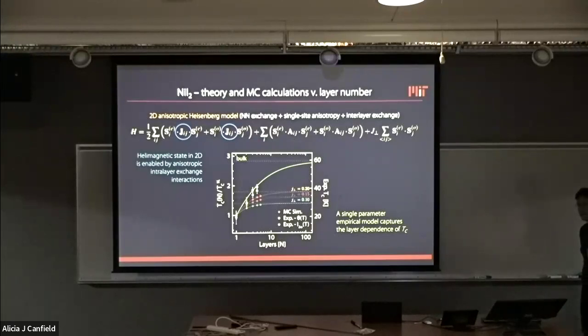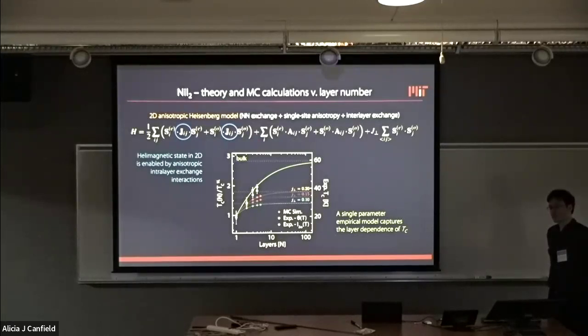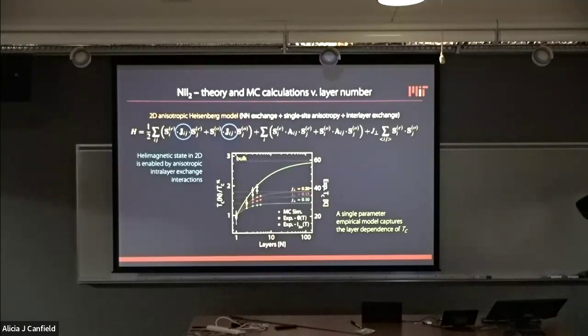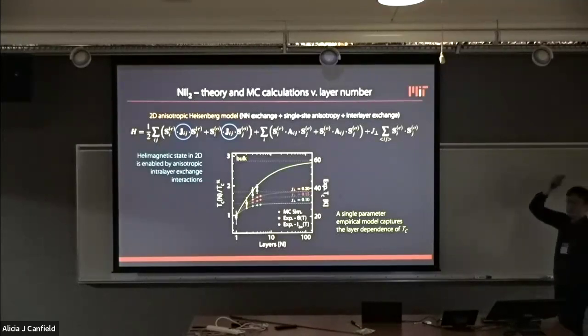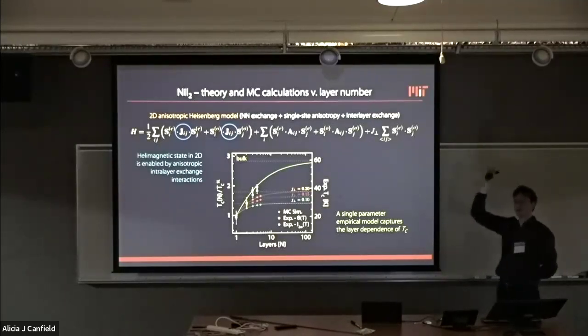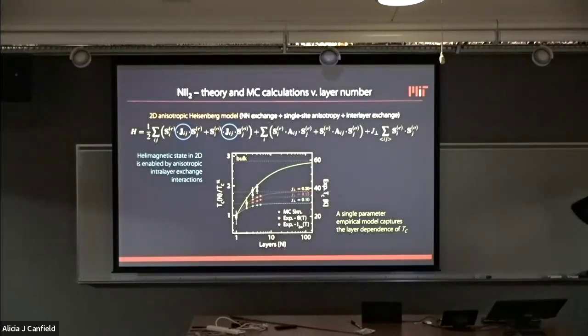So a question about this monolayer limit. If you apply a magnetic field, don't you expect a first order transition into a Skyrmion crystal? Yes, and this has been observed in several systems that start off with a 1Q state, and then you can stabilize a 3Q state. This particular material, nickel iodide, for reasons that I don't fully comprehend, but the theories do, I believe, is remarkably impervious to magnetic fields. So the spin flop field, to connect back to Igor's question, is very high, in the several tens of thousands. So the magnetic field seems to have very little effect, at least in the range that we can probe in our lab, on the magnetic flux.